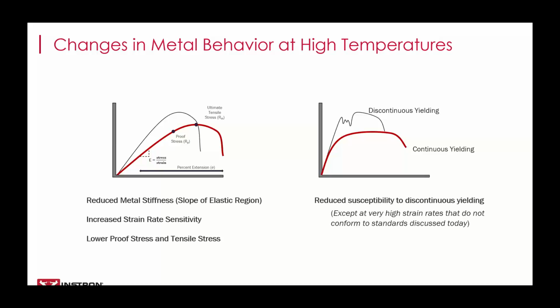Now, since the slope of the elastic region in a stress strain curve is in effect a direct measurement of this atomic force, we expect to see a decrease in the modulus as the temperature of a metal increases. This is why we see a flattening of the stress strain plot, as is depicted in the left illustration on this slide. Studies on martensitic stainless steels have shown the relationship to be about 5 gigapascals per 100 degrees Celsius. This is a good guiding point, but the relationship is of course very much affected by the particular alloy being tested and the temperature range that it's being studied or qualified for.